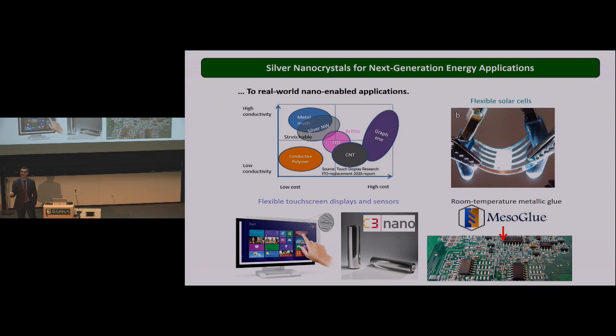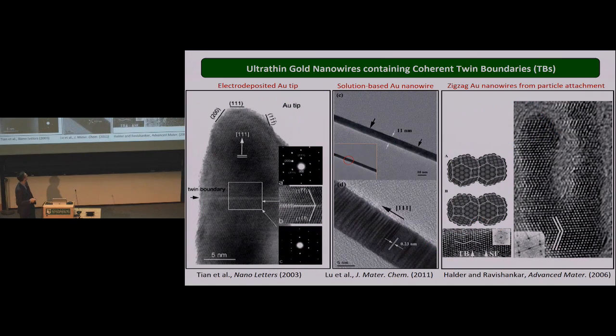So my talk will focus mostly on the material science and the mechanics of the wires made in this film, and also other types of films. So usually the wires have a perfectly crystalline structure. But they are not always perfect, okay? And so one type of defect that is found in metallic nanowires or nanoscale metals is a type of coherent grain boundary, which is a twin boundary. And here are just examples for gold nanowires. So these are very thin nanowires produced in 3 different ways, showing the occurrence of those twin boundaries.